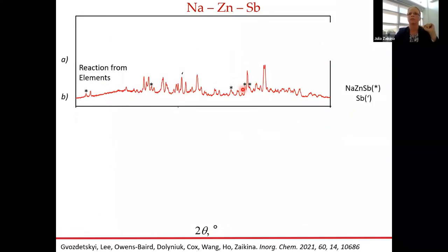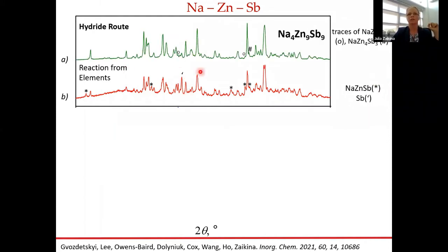So here, if you try the reaction from elements, sodium and zinc and antimony in a 4:9:9 ratio, we would get multi-phase products, and the sodium zinc antimony would be one of the major phases, as well as the elemental antimony. However, the reaction using hydride would give us almost pure sodium 4 zinc 9 antimony target phase.